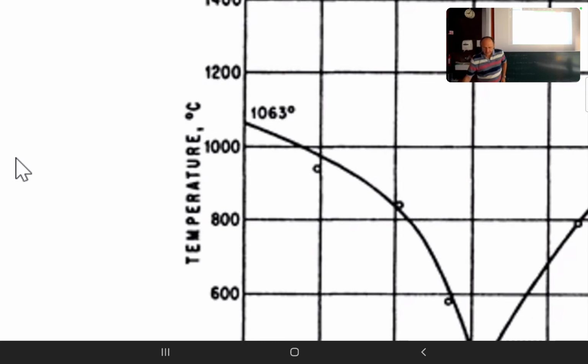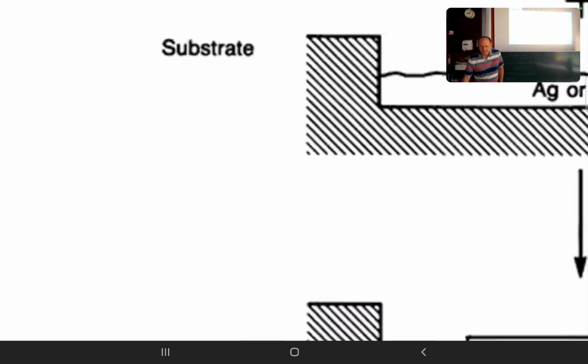And so how do we do that? So typically the silicon chip is coated with gold, but if you sputter gold onto silicon, what will happen? You put it out of the sputter machine and have a sharp look, and then the gold will roll off.